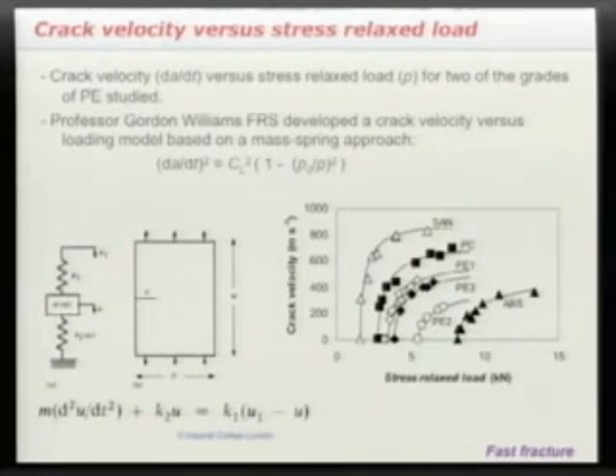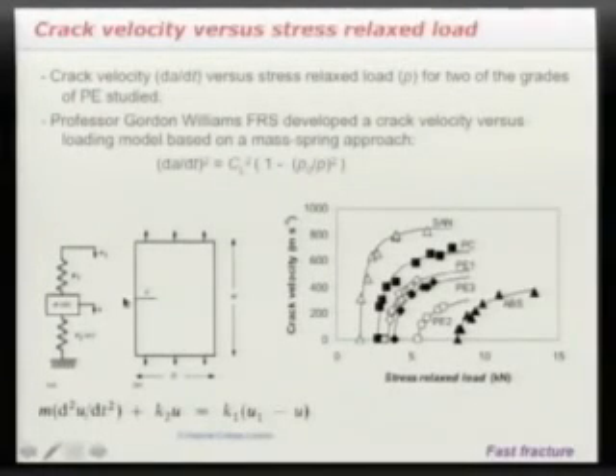And it turned out that the tougher the material, and there's a range of different toughnesses of material here, you've got up here styrene acrylonitrile, which is fairly brittle, down to polyethylene and ABS, and ABS is very tough. And you can see these materials which have a high threshold and are very resistant to fracture also tended to have a low limiting or maximum crack velocity. Well, it turned out that Gordon did some analysis of this, and what he did was to take a sample with effectively a starter crack in.